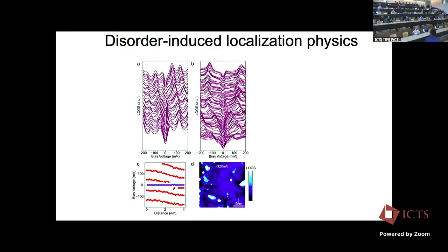Should two of these states have some funny non-local interaction between them? It's not non-local. They have to really be close enough that their wave functions overlap, and then they produce bonding and anti-bonding states. But they don't work exactly like molecules. It works on the basis of the phase relationships between these things, which is the bonding and which one is lower and higher in energy. That is different from molecules in an interesting way. But they have to be very close to each other? Yeah, it's like a hydrogen atom. Built out of these extended states then. Yeah, even though they're built out of extended states, they're really very sharply localized. So you have to bring them within touching distance to get some interaction.